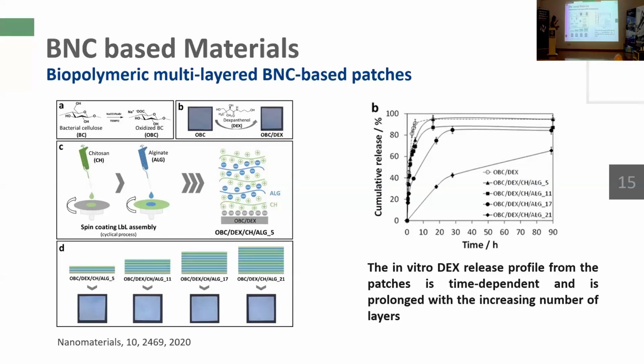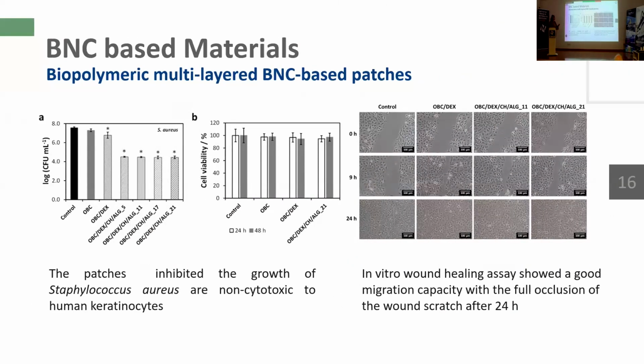Obviously, depending on the polymers that we select and use in this system, we can incorporate additional properties. In this case, since we use chitosan, these membranes also present antibacterial properties. They are, of course, non-cytotoxic, and the presence of the drug that, in this case, I think I forgot to say, was dexpanthenol, a common drug used in skin formulations for skin regeneration, improved the wound closure in this in vitro model.